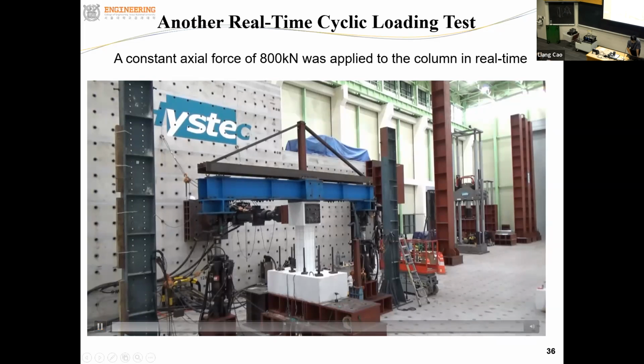We apply the axial force. Okay, let me stop the video here. So you can see some bending deformation here compared to this reference frame. Okay, if I go back this test setup to the original state, then you see the bending deformation between these two. So you can see the deformation visibly by pulling. We pull down the beam here and there. Then that bending deformation is maintained throughout the cyclic loading test.